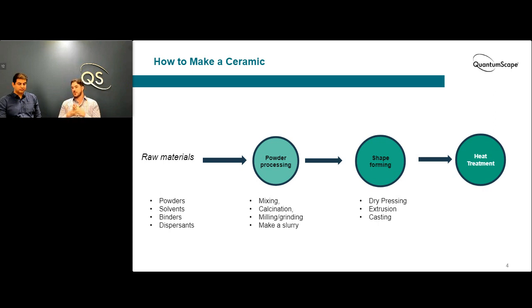But in all cases, you're trying to accomplish the same thing, which is to raise the temperature of your powder to roughly 80 or 90% of its melting point. At that point, the particles, which are loosely bound, start to fuse together. That process continues with more time and temperature until all the free space, all the porosity, is expelled. Those particles then really fuse together and form that polycrystalline structure that we showed in the earlier micrograph. And when you cool that down, you're left with your processed ceramic material.